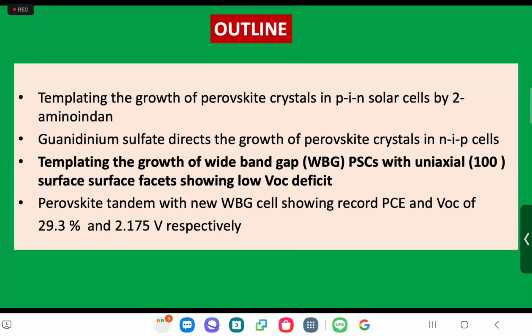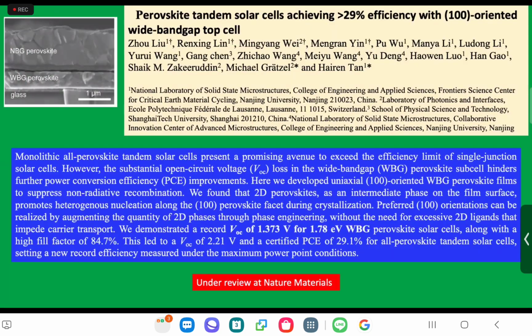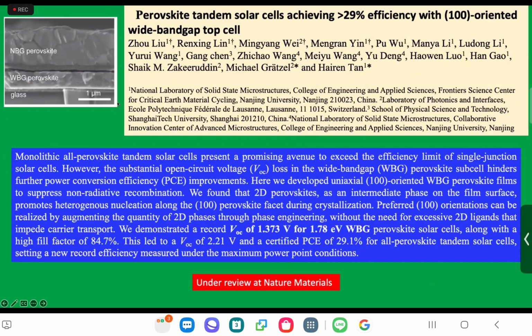So when you do that, you get stunning changes. And so the crystallization of the perovskite is directed by a 2D film that also forms on the substrate spontaneously, okay? And so this is something that is under review in Nature Materials. And so we hope that it will go through, and later we will use that material as a wide bandgap perovskite, okay? So it's a wide bandgap material, and